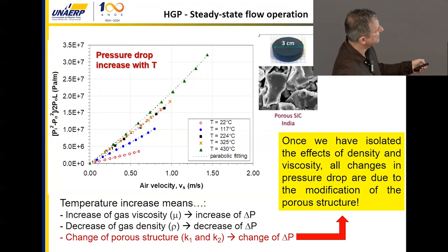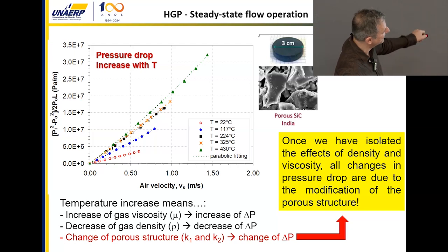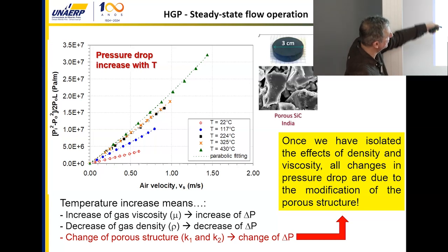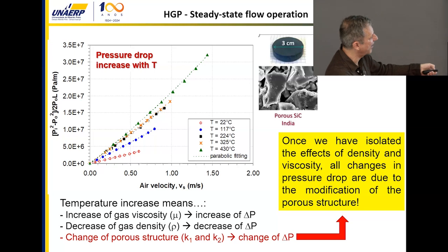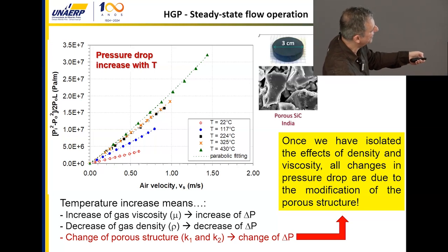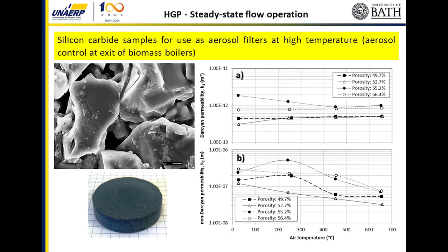This is a typical set of data where you get this silicon carbide filter, and we test from 22 degrees to 430 degrees, and you have different curves. The pressure drop is increasing, but it's increasing because the gas viscosity increases, but also there is a density decrease. But after all, we can check if the structure changes. And we see that it changes, the K1 and the K2 change. So the microstructure is opening or closing due to thermal expansion. Because sometimes you predict the behavior at room temperature, but you're going to apply the material at very high temperatures. So to predict it there, we have an equipment that measures at the real temperature of the event.